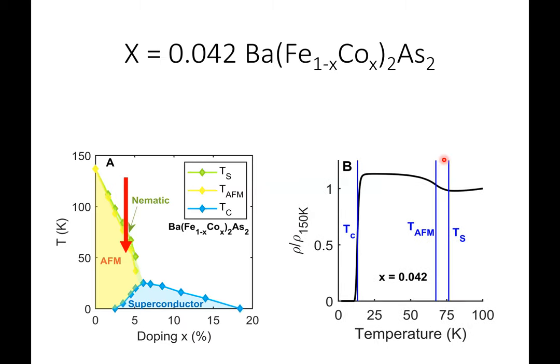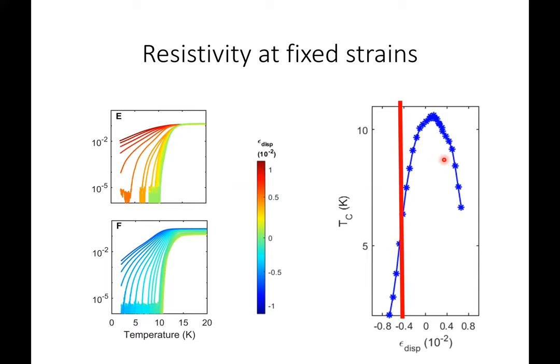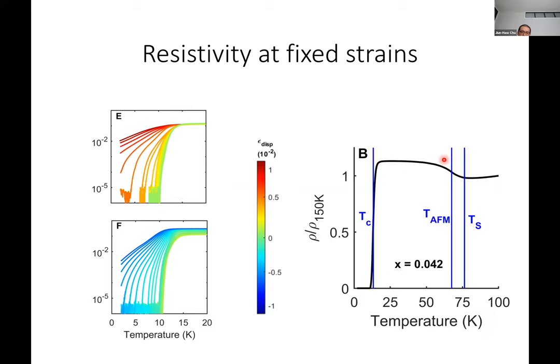My curious question is whether the magnitude is similar between compressive and tensile strain in terms of shifting TN? So the interesting thing is that the anomalies actually almost disappear in tensilely strained crystals. I see. So it's basically looking like an almost flat, straight curve as a function of temperature for this.